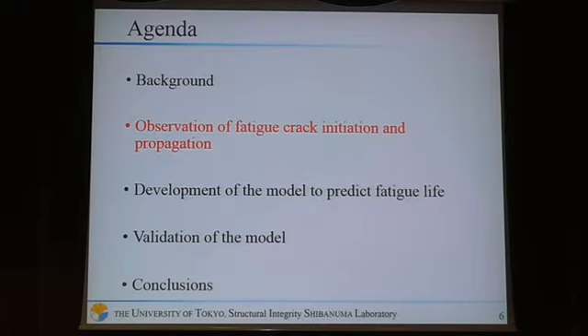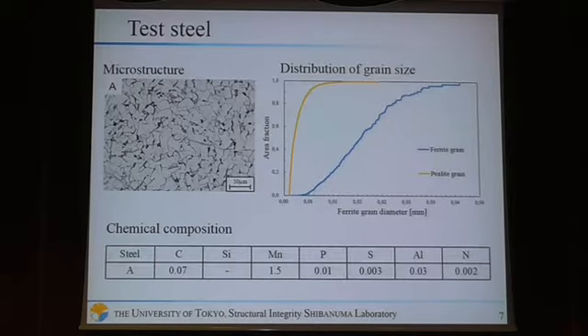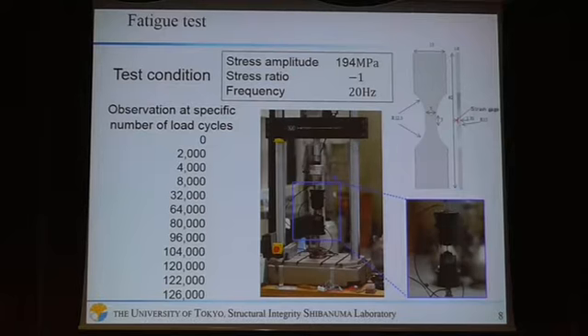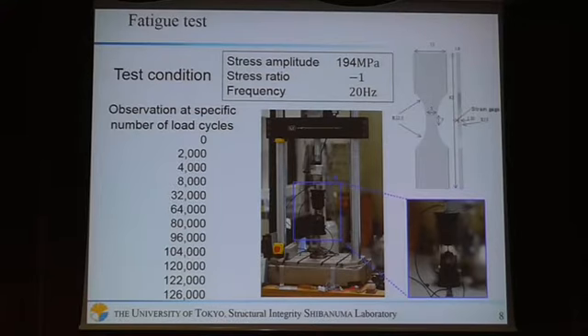Next, observation of fatigue crack initiation and propagation. In the fatigue test, we use this test steel. In the fatigue test, this specimen is used. This specimen has a notch in the center, and the place where a crack can initiate is limited by this notch. Test condition is on this table.